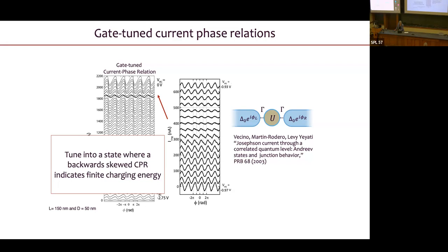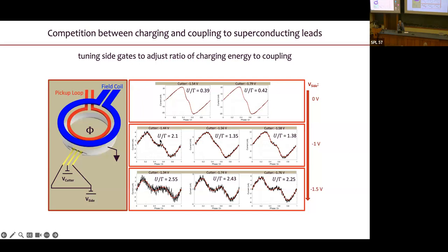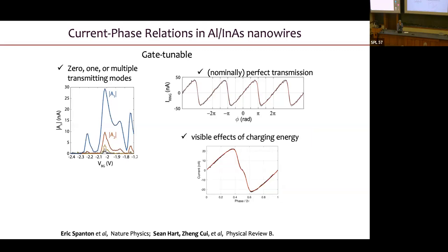Then we verified that we really are seeing the tuning through a correlated level by building a different structure in which we could tune the ratio of the charging energy to the coupling from the gates. Our collaborators at Microsoft Station Q did some very specific modeling of what the mode structure in these indium arsenide nanowires might look like, and it agreed qualitatively with what we're seeing. So we're pretty sure that we really saw that. The modeling of the physical mode structure was done by Andrey Antipov and Roman Lutchyn at Microsoft Station Q in Santa Barbara.